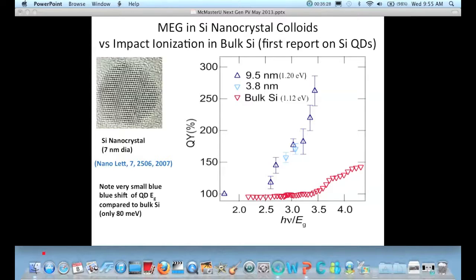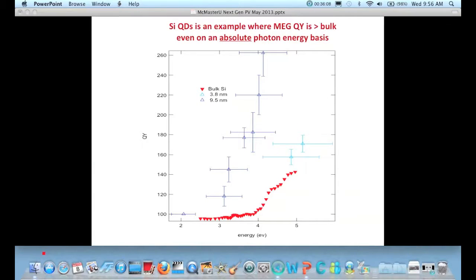But even if you plot for silicon, you can get very nice quantum dots of silicon, perfect crystal structure with no defects, either in the bulk or on the surface. Even when you plot it, in this case we're plotting it normalized, you see it's much better than the bulk, which we saw before. Nothing happens until you're outside the solar spectrum. Here you see that you begin to get very efficient MEG at a lower photon energy relative to band gap, and that's a good thing. And even if you plot it on an absolute scale, you still can see a threshold earlier than the bulk and with a steeper slope.